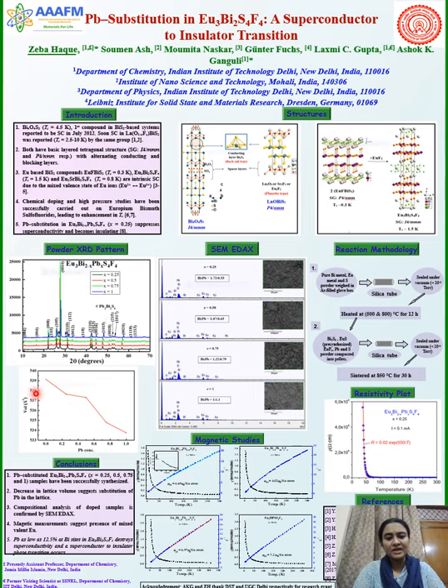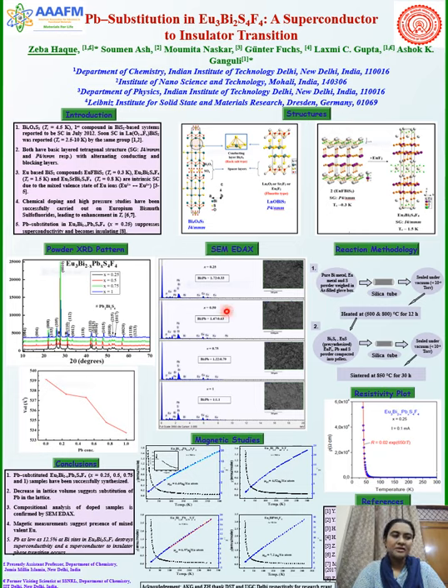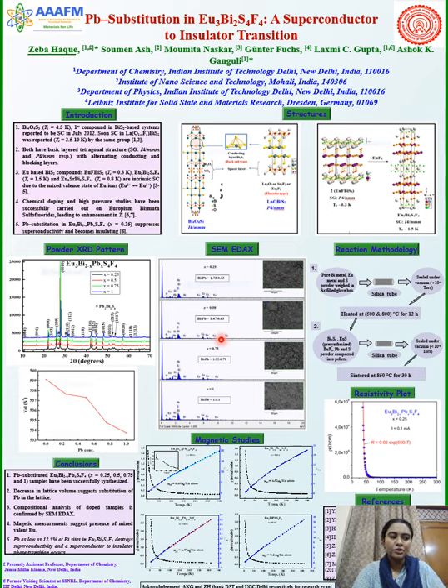The variation of lattice parameter and hence the lattice volume is found to shrink gradually with lead substitution, which suggests that lead doping has been successfully achieved in the system. SEM-EDAX compositional analysis was carried out for all compounds, and the calculated molar bismuth to lead ratio in all samples was very close to the nominal value within measurement accuracy.